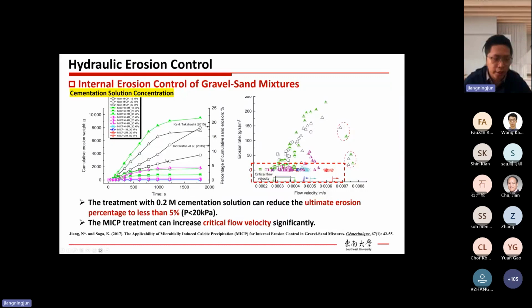Obviously, if we only have a little bit of cementation, the erosion control effectiveness is not that good. In some cases, it could even be worse than the untreated case. But if we have a lot of MICP, with more cementation solution concentration, then almost no erosion. And in addition to the erosion rate, if we look at the erosion rate versus flow velocity relationship, we also find that with heavy cementation, the critical flow velocity is larger than the moderate or slight cementation case. So it means that MICP treatment could improve the critical flow velocity. And the more cementation solution concentration we have, the higher the critical flow velocity.